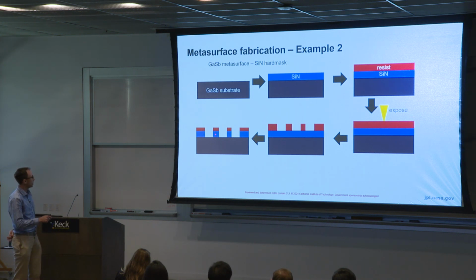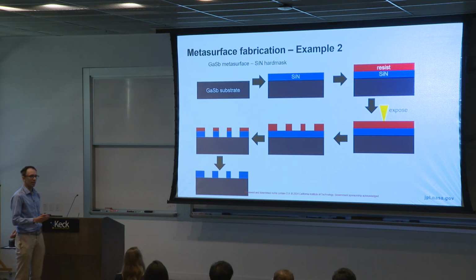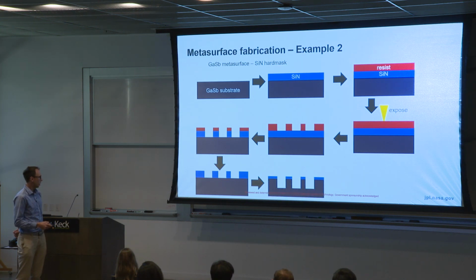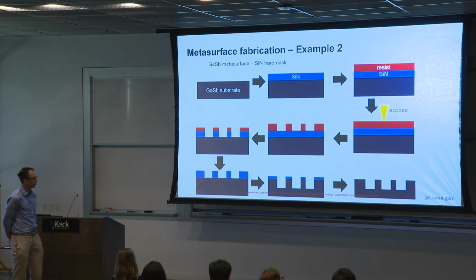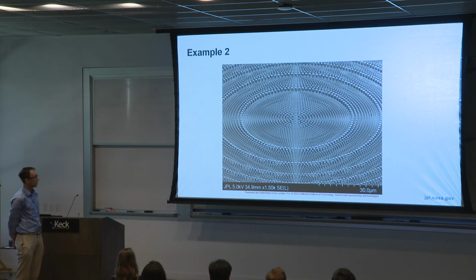So using some kind of anisotropic etching, you transfer this pattern into the silicon nitride. Then, to remove any erosion effects, you would remove your photoresist or E-beam resist. And now you use a third type of etch, because the etching we did for the silicon and the silicon nitride does not work at all for gallium antimonide, which is a notoriously difficult material to etch. So you can then transfer the silicon nitride pattern into the gallium antimonide below. So you have gallium antimonide pillars. And then, if you're lucky, you remove the silicon nitride without damaging these delicate nanofeatures. So that might look something like that.